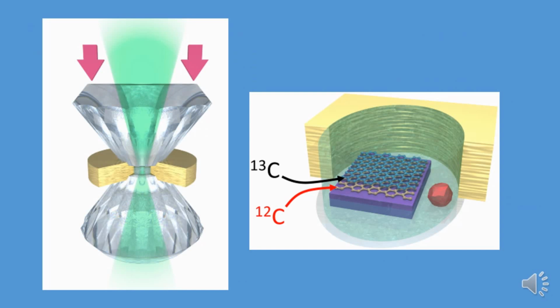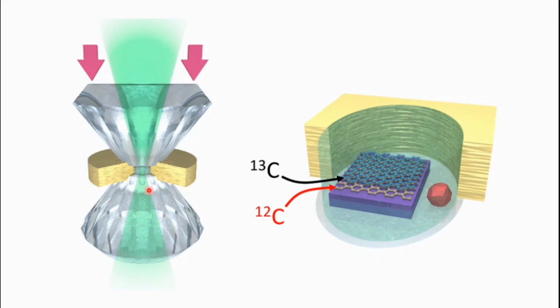The sample was submitted to high pressure using a diamond anvil cell. This setup allows to compress a system composed of the bilayer graphene sample made of two isotopes and supported on a silicon dioxide substrate in a cavity between two diamonds. The substrate and bilayer graphene system is immersed in a fluid, the pressure transmitting medium. A ruby chip allows to calibrate the internal pressure using its luminescence. We focused a laser beam to probe the graphene phonons using Raman spectroscopy.